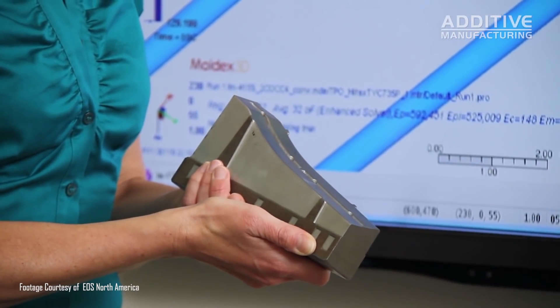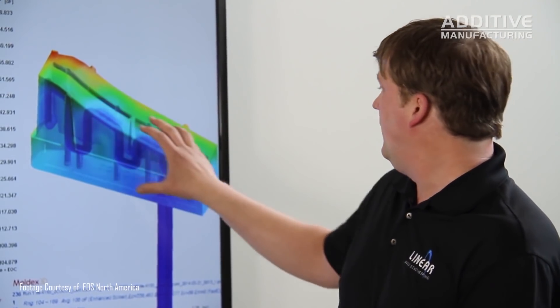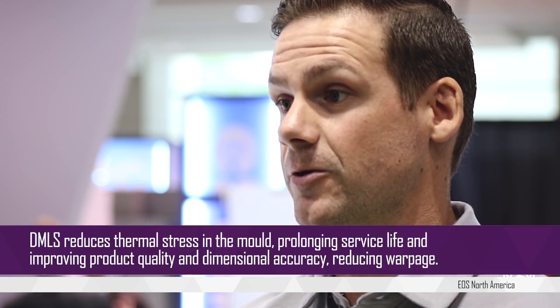The example that you've shown us is a relatively small tool. How big do you think we're going to get with additively manufactured tooling? The largest machine that we currently produce is about 400 millimeters, and you can build full field on that machine, so a 400 millimeter square insert would be the largest part we can produce on EOS. There are some challenges right now as the industry is evolving, and those challenges pertain around heating and cooling. The bigger the parts get and the wider the field we're trying to cover, as one area of your part has already cooled because the laser finished fusing the powder together and is over on the far end of your workpiece, one part is going to be hot while the other is cold — that could lead to some twisting, warping, or concerns with the metallurgy. Whereas when it's more compact, we get much more uniform heating and cool-down of the part, which gives us better part qualities.